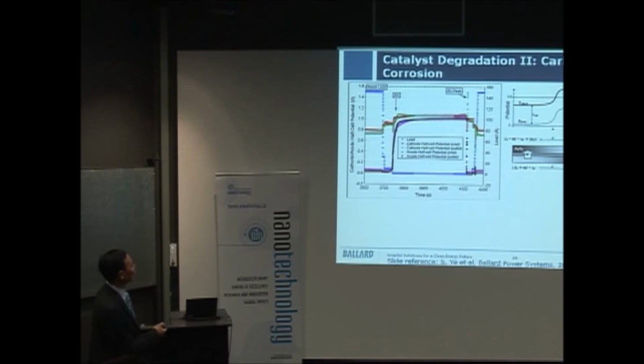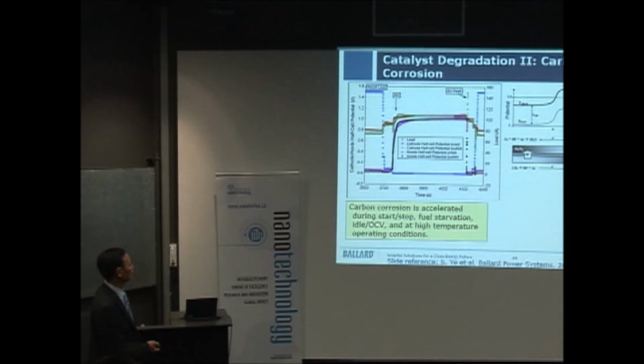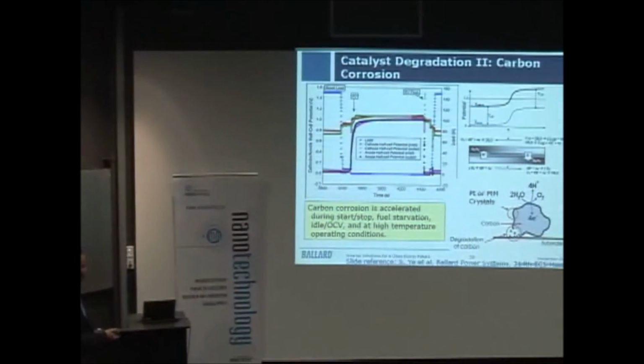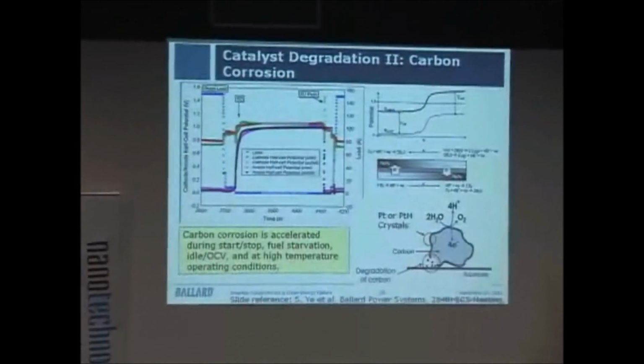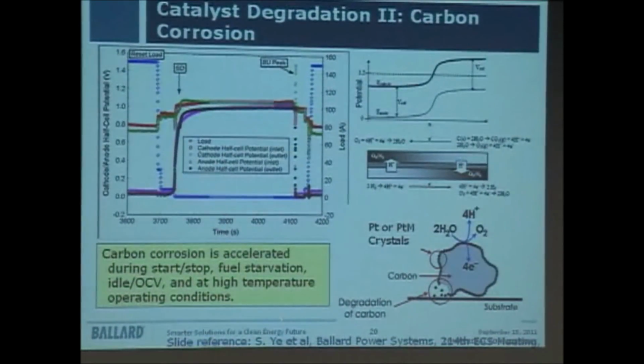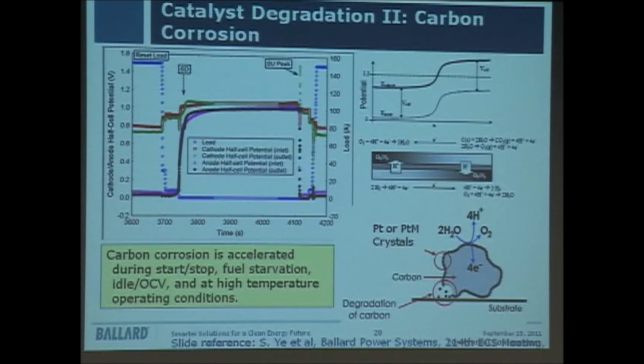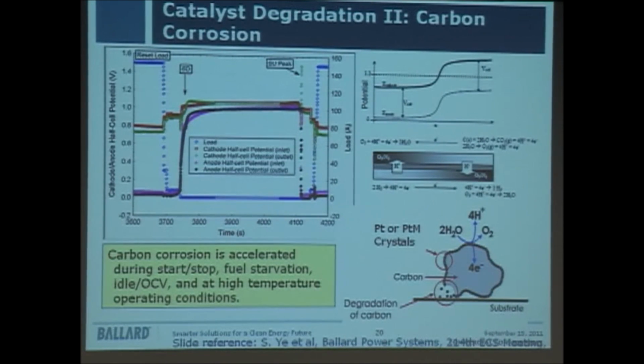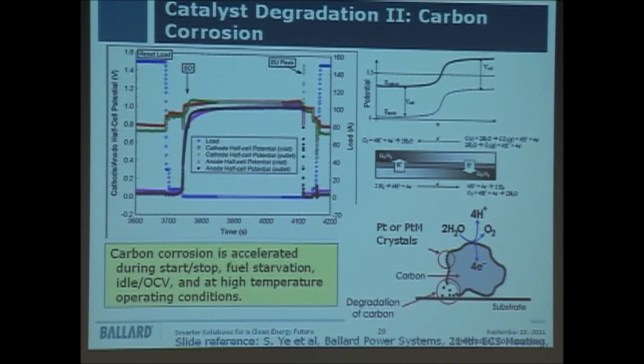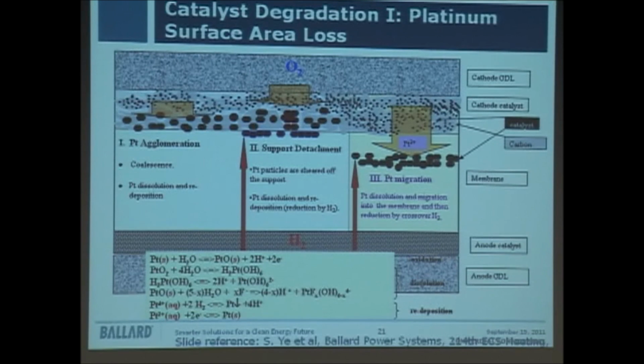So when you start, sometimes the peak will go very, very high, sometimes even beyond 1.4 volts. This high cell voltage will accelerate catalyst dissolution and support carbon corrosion. One example is that when the carbon corrodes, the platinum or platinum alloy catalyst will also dissolve or even leave the carbon support. So for that reason, catalyst support stability is extremely important for us to maintain our fuel cell performance over a lifetime.